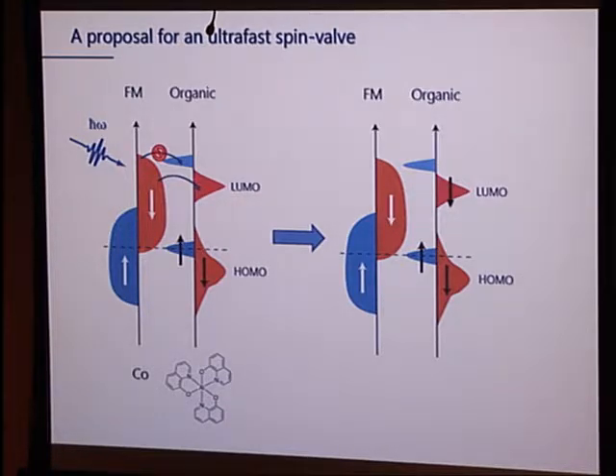We are going to populate that with an ultra-fast laser pulse, and that's going to lead to selective charge transfer, which must somehow be spin-conserving, from the density of states into the molecule. It could also be reverse. It could be from the molecule into the ferromagnet. And if that happens, then I should get preferentially only one spin being injected. So I have a spin filter, and that should occur on really fast timescales. That was the original idea.